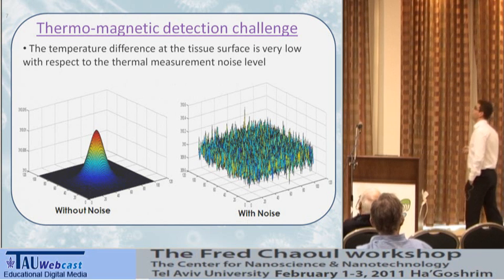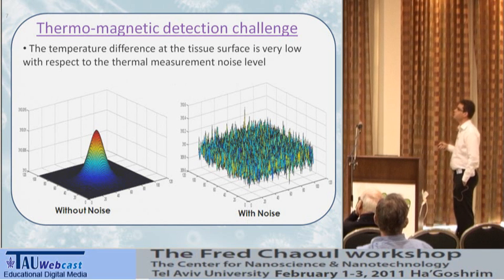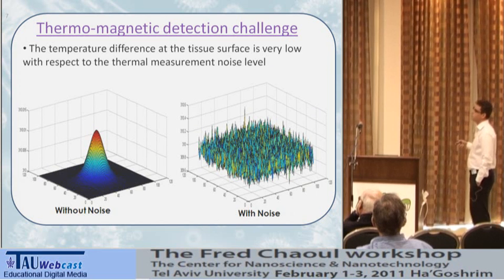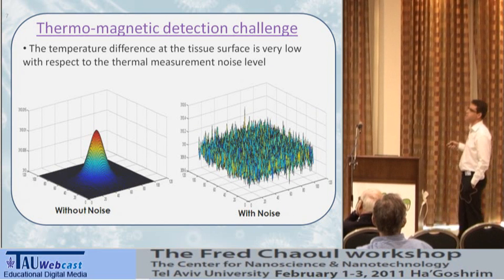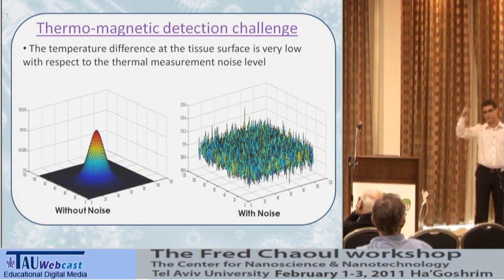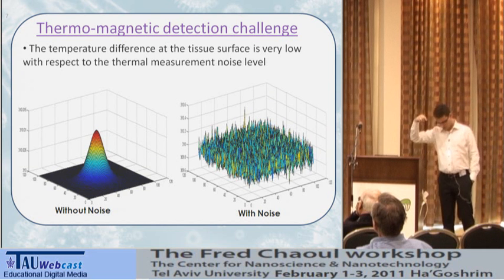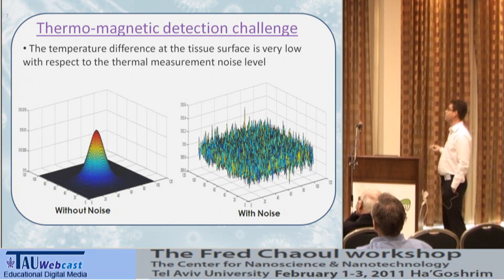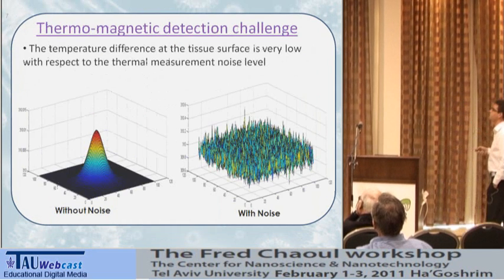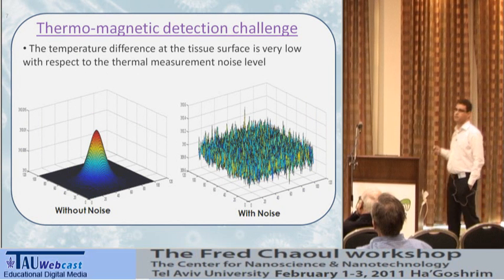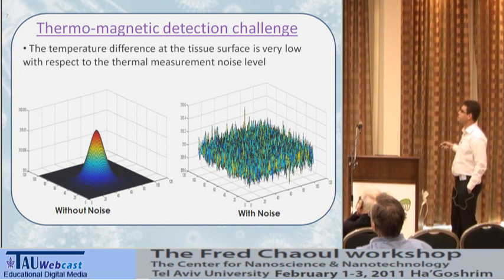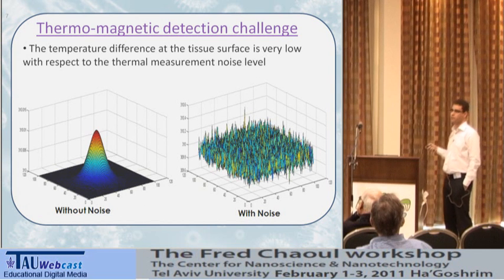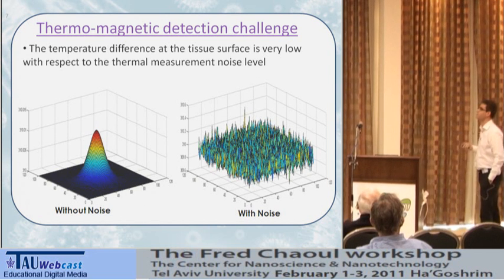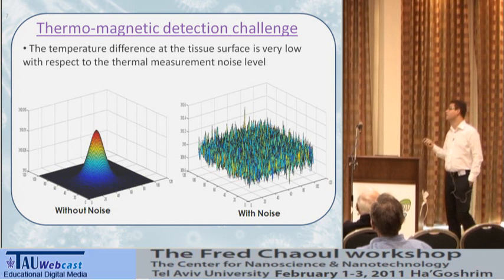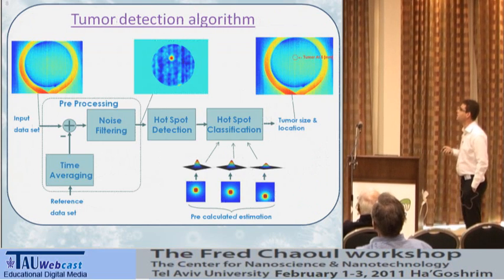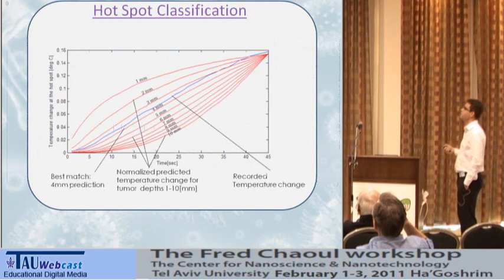Okay, so one thing that we saw pretty quickly was that detecting a tumor, if you don't assume any noise, is very easy. You just see a nice Gaussian pattern after a while on the skin surface above the tumor location. But if you take into account the noise, like the thermal noise of the camera, you just don't see anything anymore, because this pattern is very, very small compared to the noise we have in measurement. So in order to overcome this, we developed some signal processing model,